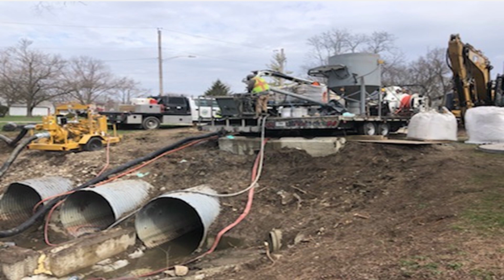On a lot of bigger jobs, we've got a silo, and you can see these white super sacks up here in the right-hand corner. Instead of 65-pound bags of mortar and having a big pile of empty bags at the end, you take these super sacks and lift them up on top of this silo. You've got a cutter up there that'll cut those bags open. All the mortar flows down into this silo, and then as you're ready to mix, you take this auger, this swing arm, and pull it over to your mixer.